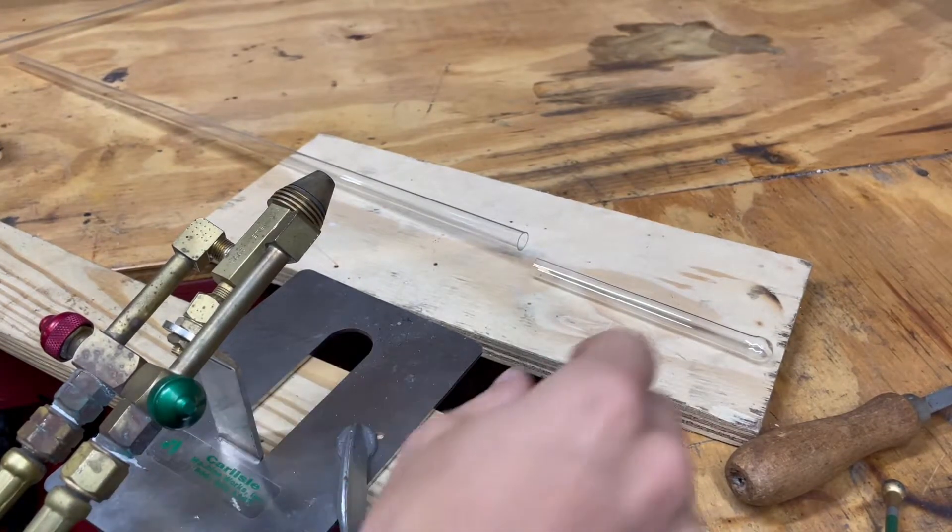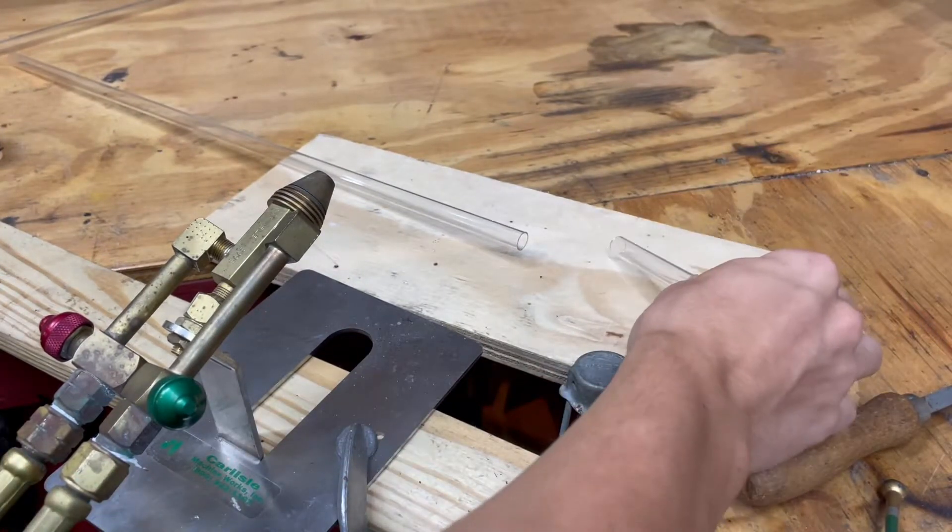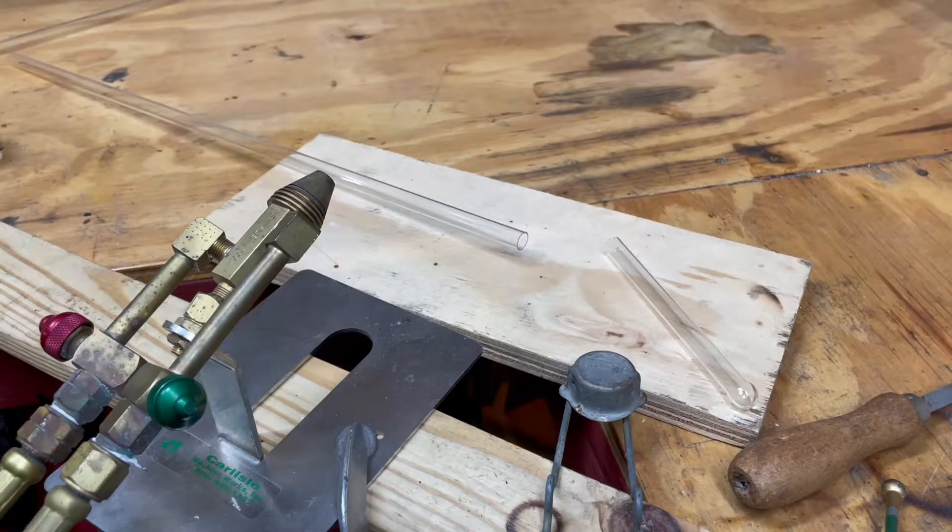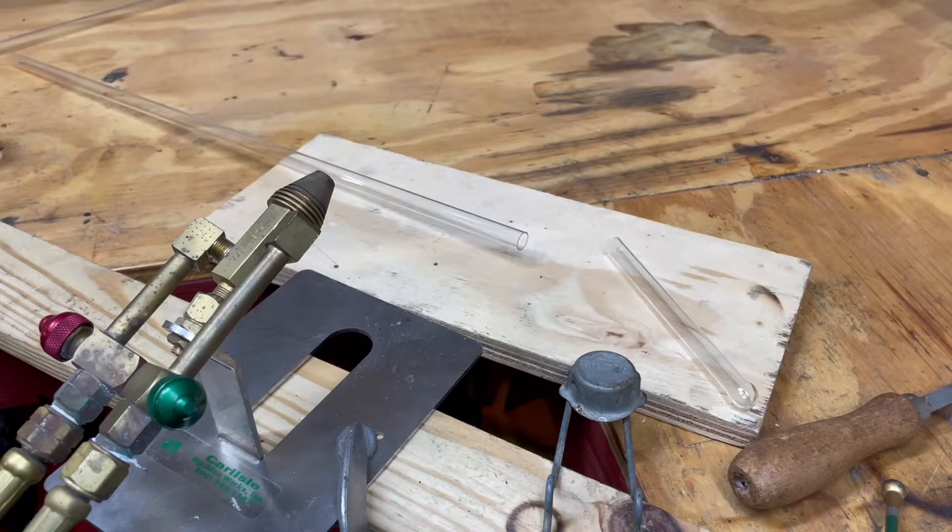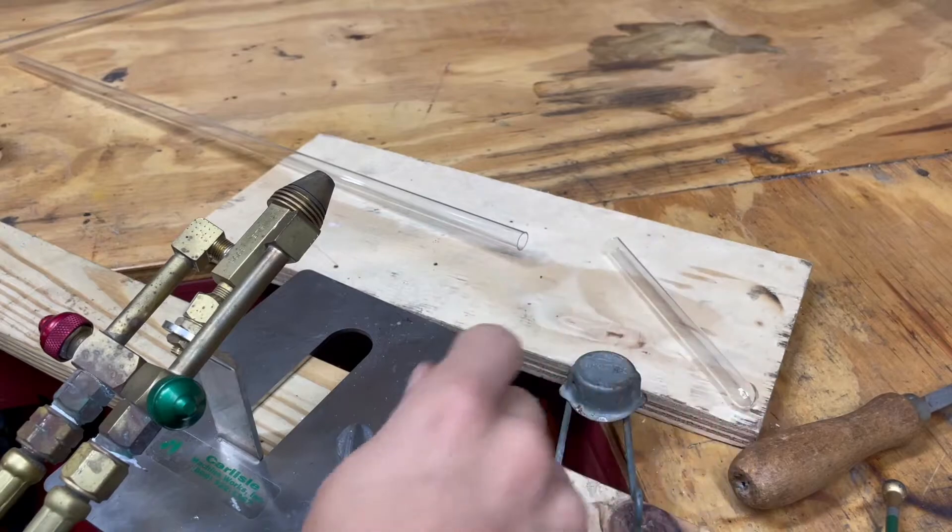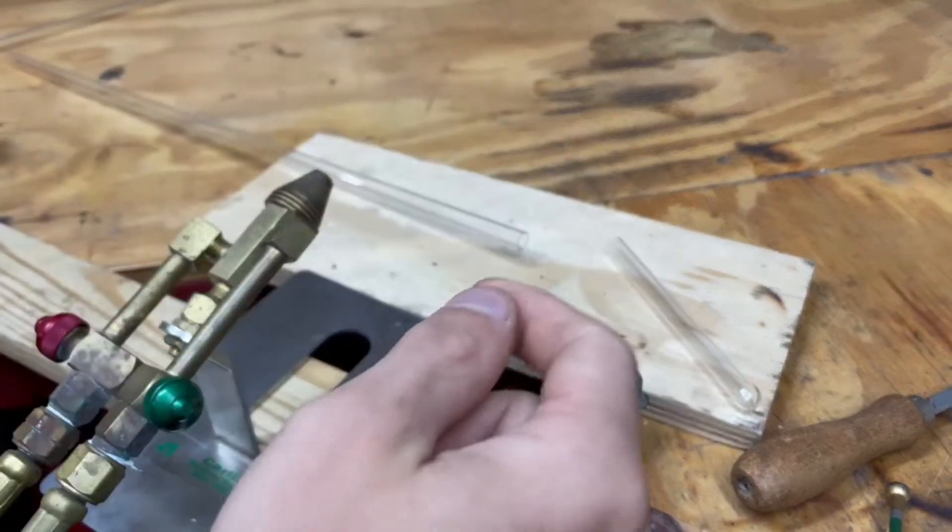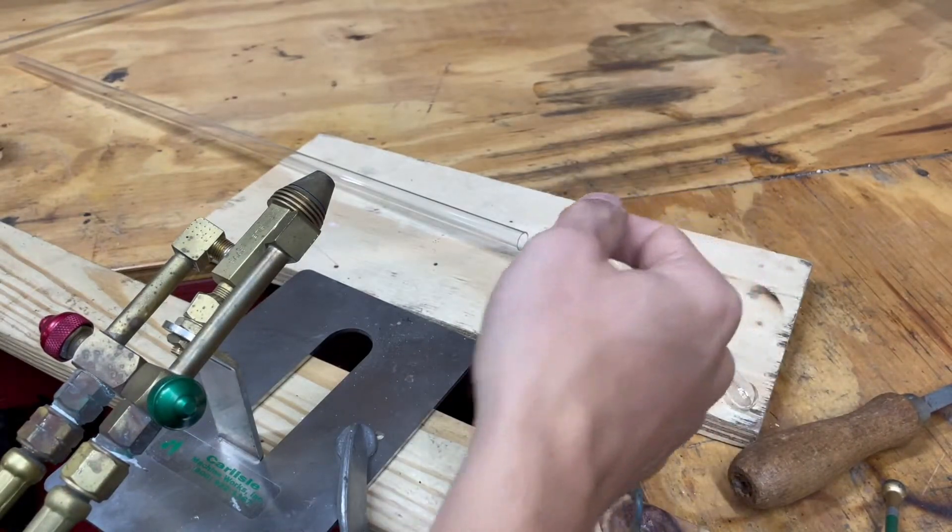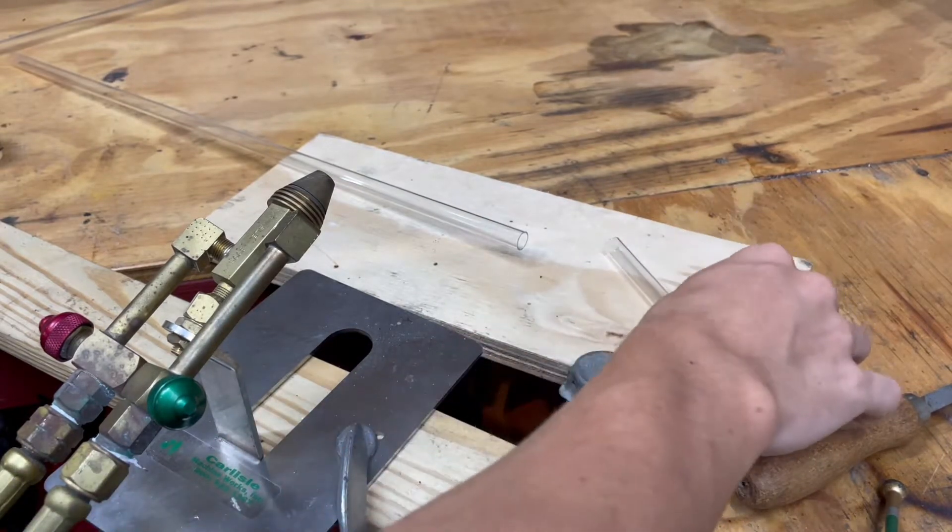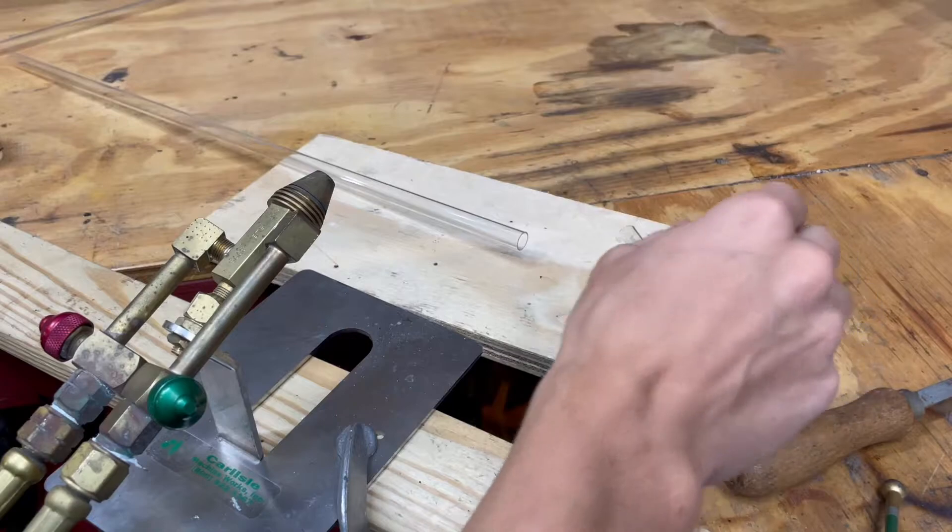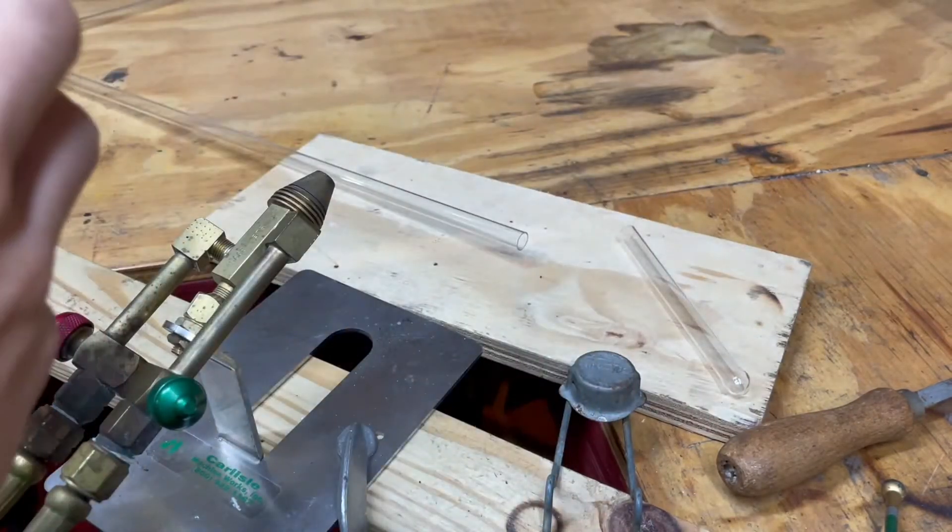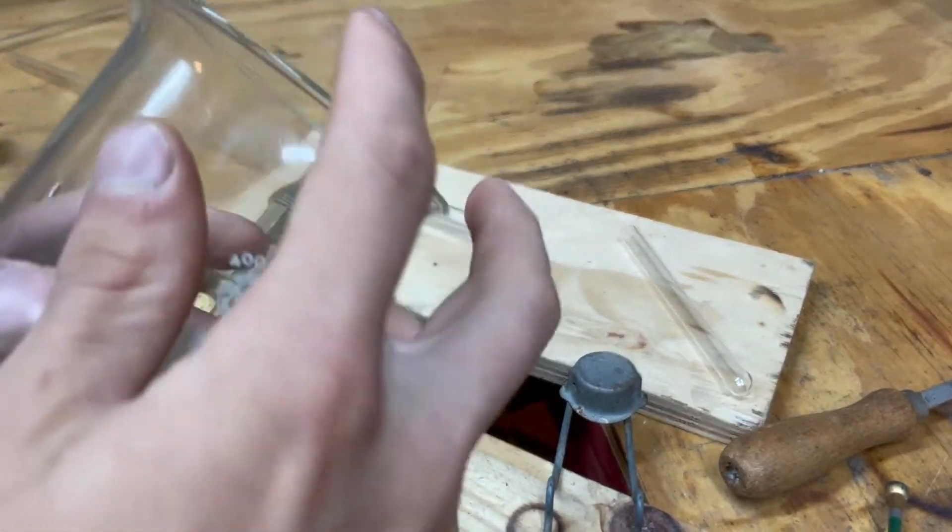Okay great, now you have your glass cut. But it has this sharp jagged edge on it. What to do now? Well you do a process known as flame or fire polishing. With this you just bring it into the torch and melt the glass around it creating a nice smooth end. Now fire polishing isn't reserved for just cleaning up tube that you're working on. It also can be used for different repairs. It's one of the more common repairs that you'll be making on things.